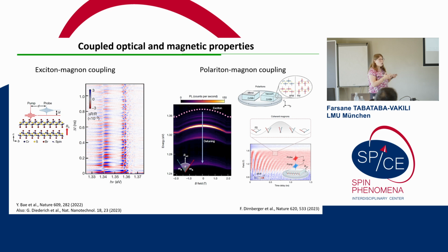And then there's been a lot of other cool stuff happening. There've been demonstrations of exciton-magnon coupling here in this work, for example, from just a couple years ago, using pump-probe spectroscopy and canting the spins a little bit with an out-of-plane magnetic field, and looking at the transient reflection, they were able to observe these oscillations, which are a hallmark of exciton-magnon coupling. And then Florian here, in this very nice work, demonstrated polaritons for the first time in CrSBr, and then also showed polariton-magnon coupling using the same method. So the idea was to introduce this material a bit, but somehow you're all working on it, so.